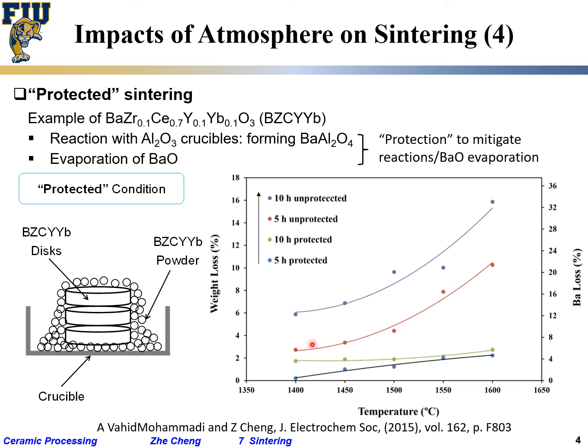And then when we do this so-called protected, at least covered, we manage to get the loss below roughly 2%. Not 0, but something that we can handle, which we can tolerate. Okay? So you see the example.